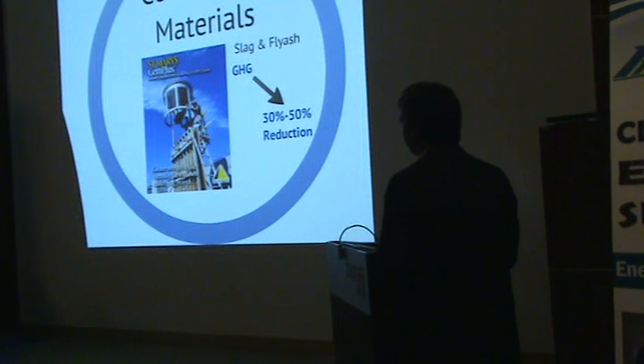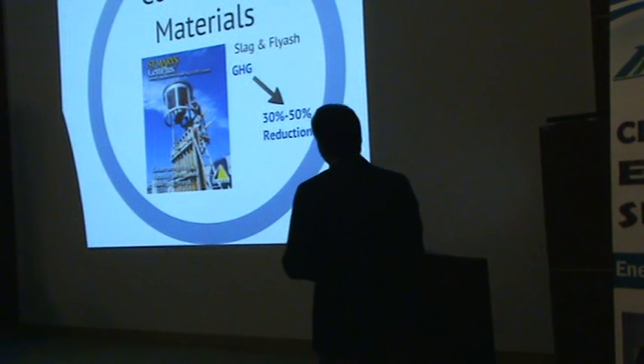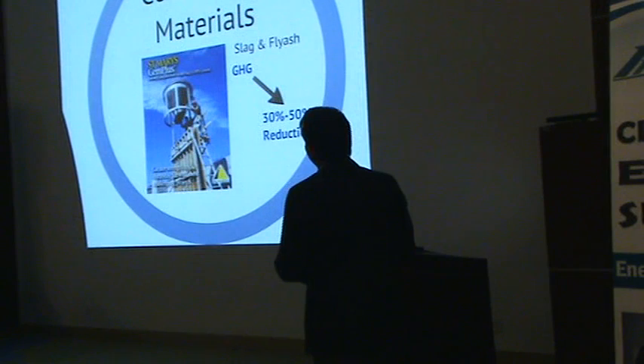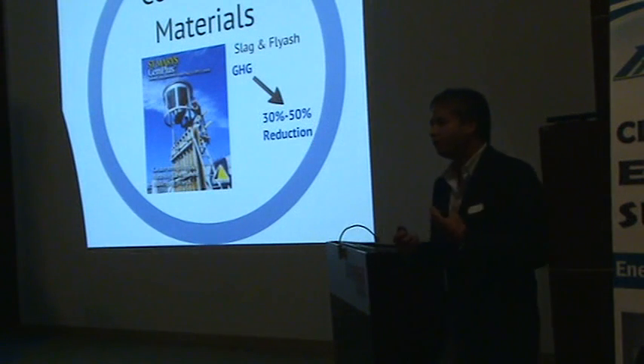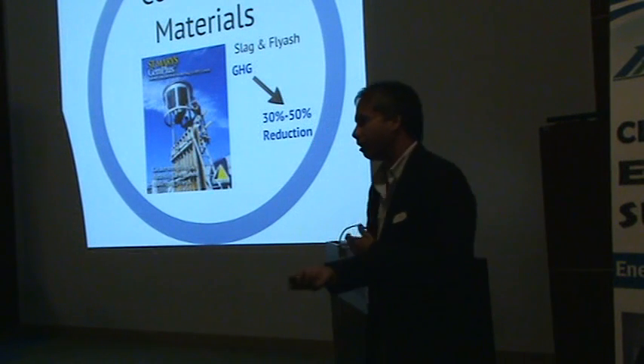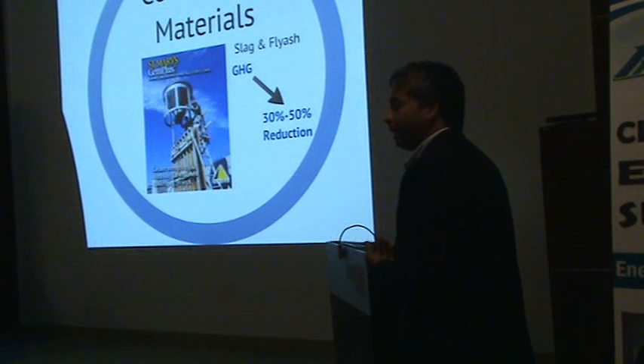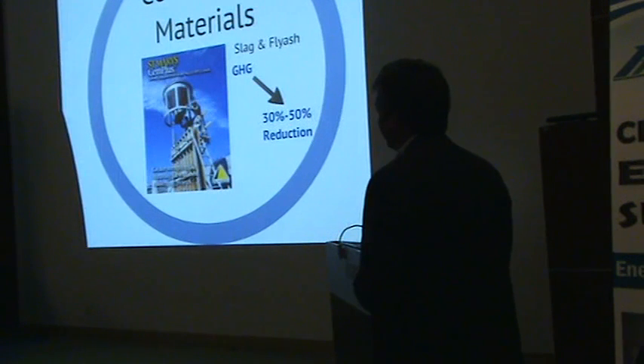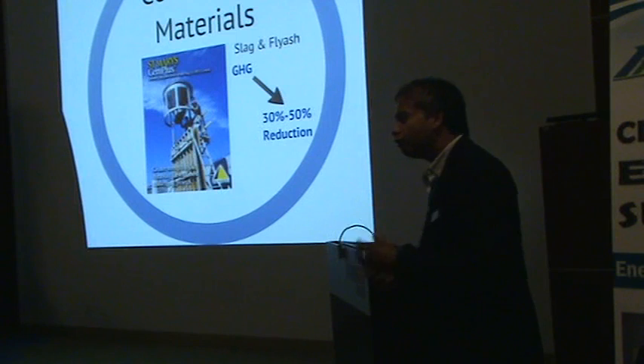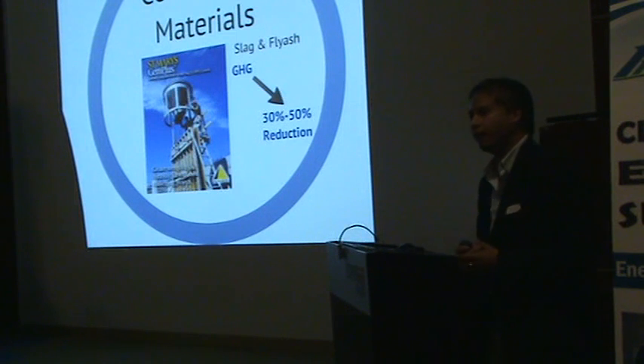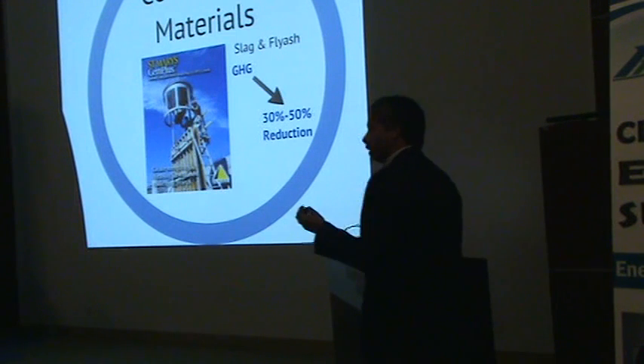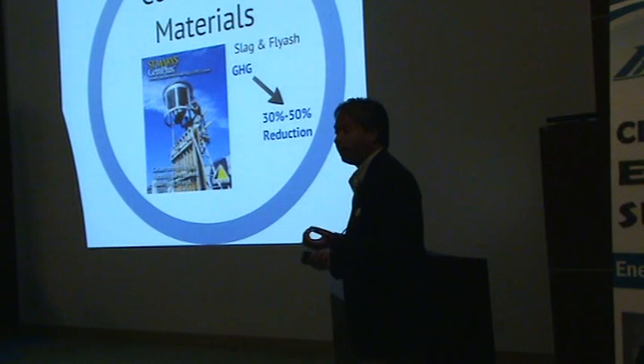So some of the things we've done is we've looked at cementitious materials, wastes from the steel industry like slag and fly ash from coal-fired power stations can be used and mixed in with cement into concrete and reduce the amount of cement needed by as much as 50%, which reduces the greenhouse gas by 30 to 50%.